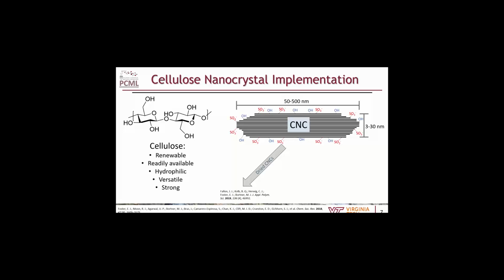However, once you remove the water, you generally neutralize those charges with counter ions such as sodium, and you tend to have problems with aggregation that you can't ever redistribute the CNCs very effectively. There's a lot of current research on trying to redistribute them, but a lot of it doesn't work very well. So another method is to use solvent exchange, where you can swap out the water for something like polyethylene glycol, and you can then evaporate off your water, and then you suddenly have your CNCs in polyethylene glycol.